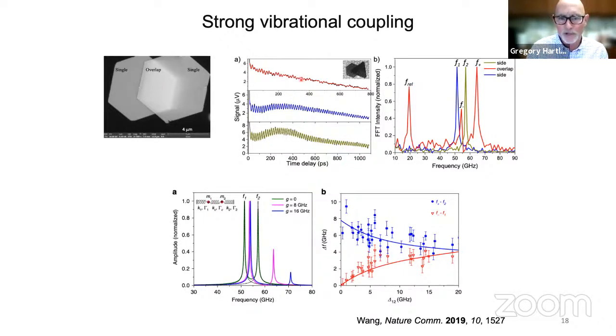When you're in the overlap region, you see a much more complicated pattern, with multiple frequencies. These are the Fourier transforms. The blue and greenish curves are the non-overlap single plate regions, where you see a single frequency corresponding to the breathing mode. In the overlap region, you again see 2 frequencies up in this spectral region, but they're shifted because the 2 vibrations are coupling to each other. There's also a lower frequency mode. We call that the relative mode. That is the 2 plates just vibrating relative to each other. It's not the breathing mode, it's the plates moving independently of each other. So you see a vibrational coupling.